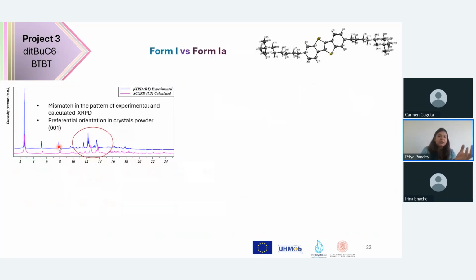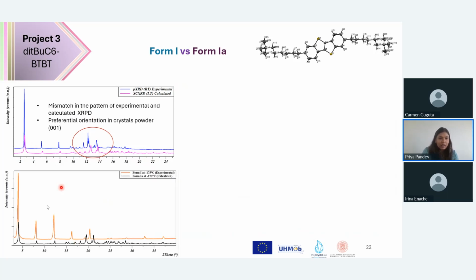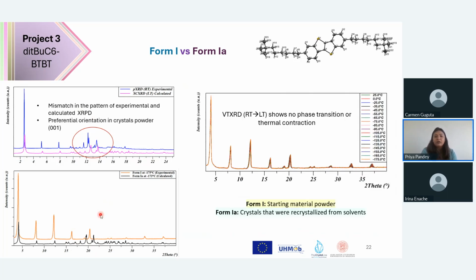So when we obtained the material as a starting material from ULB, we called it form 1. We recrystallized it, did the powder XRD of the forms, and mainly we obtained preferentially oriented peaks, which were more or less matching with the powder. But thanks to synchrotron, I obtained very high quality data and then compared it to the crystal simulated powder XRD and saw that there was a slight mismatch, which we thought could be due to temperature difference. But again, collecting the same at the same temperature, we found that the mismatch persists. We thought it could be due to a bit of transformation or thermal contraction.